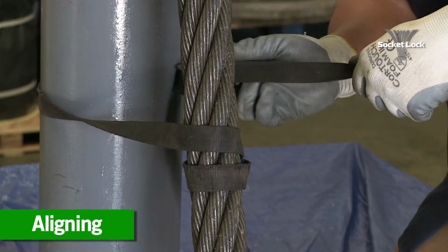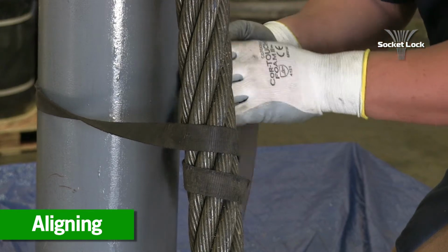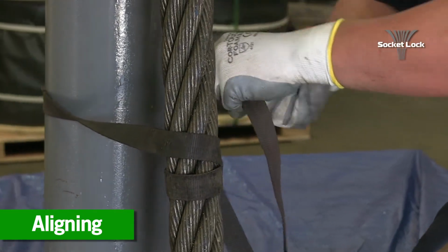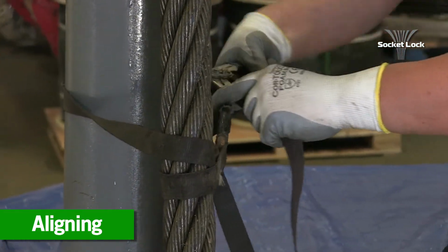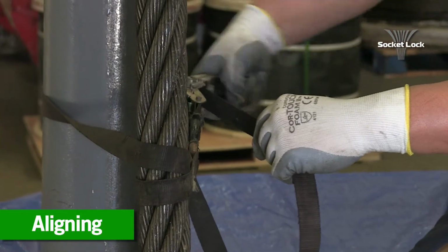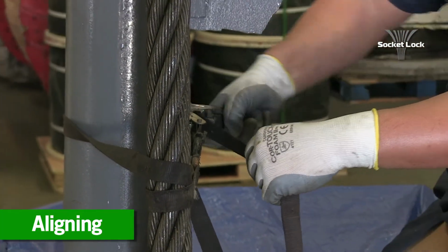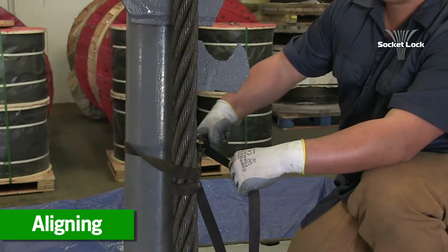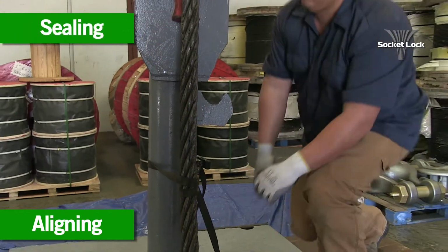If the rope is not properly aligned while pouring the resin into the socket, the rope will be set at an angle. Testing has shown that when this occurs, the rope is likely to break at the base of the socket below the catalog breaking strength of the rope.